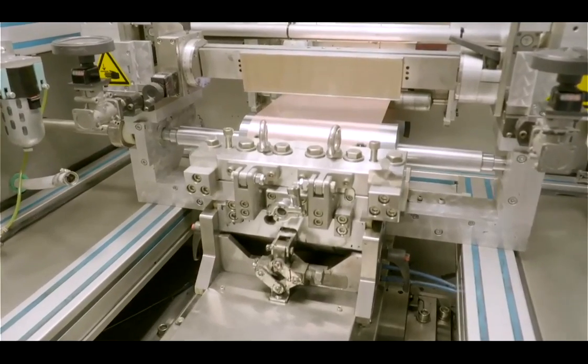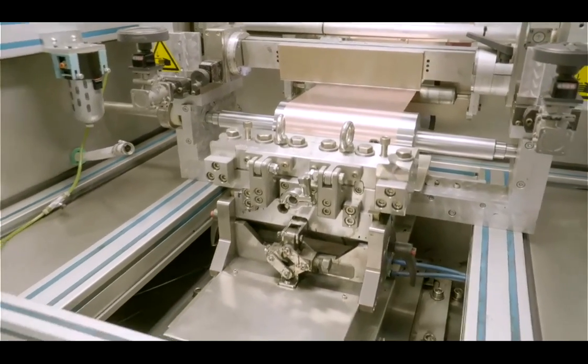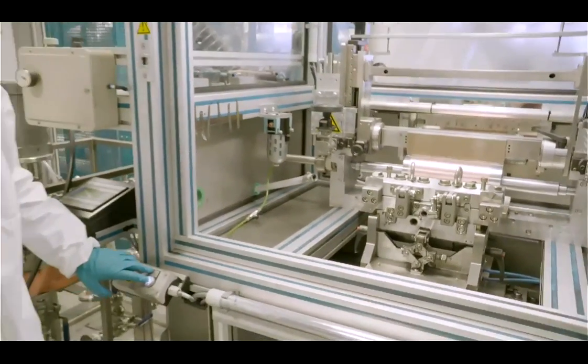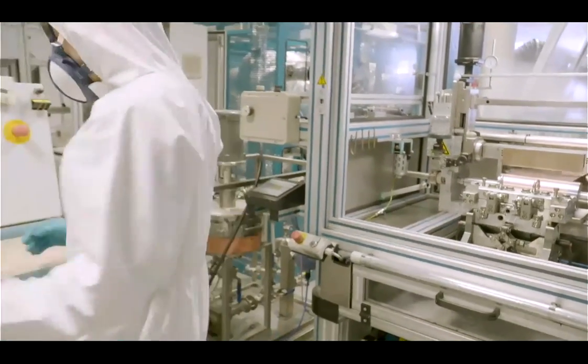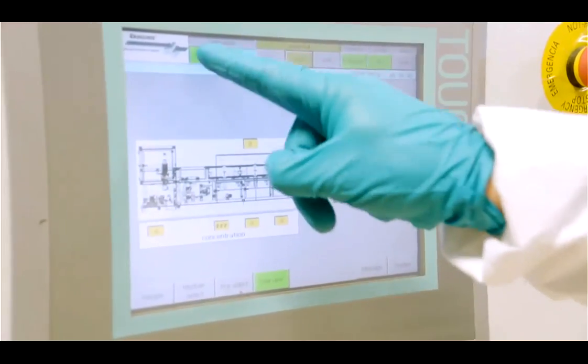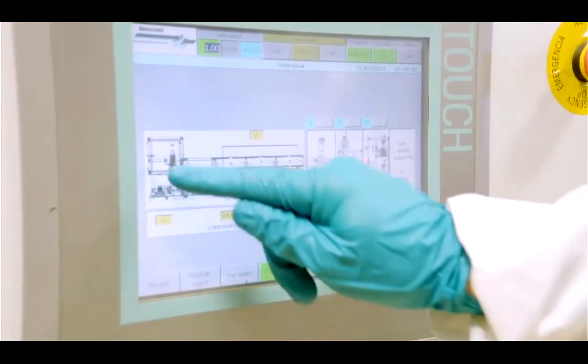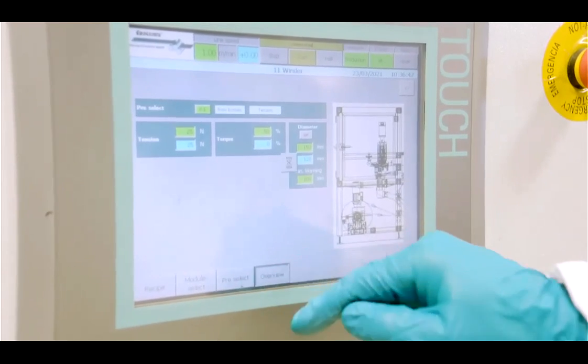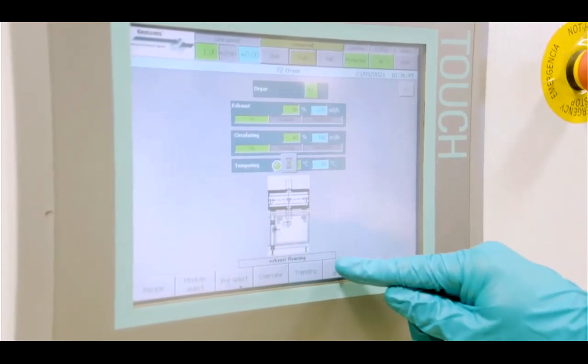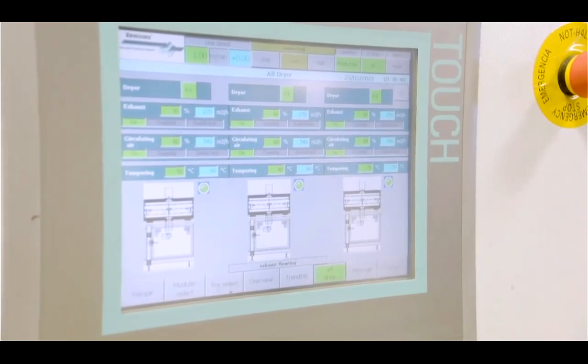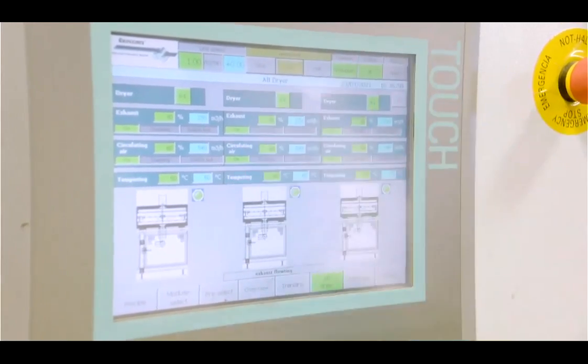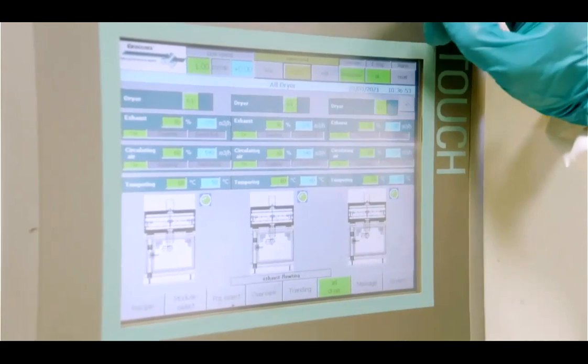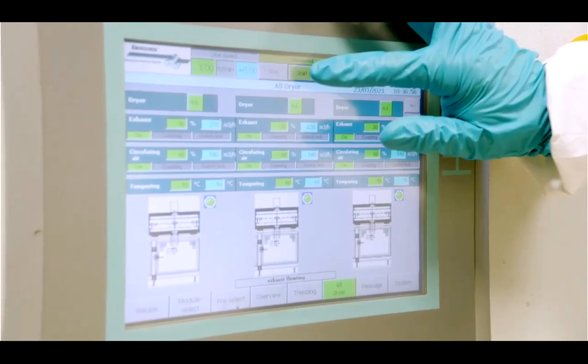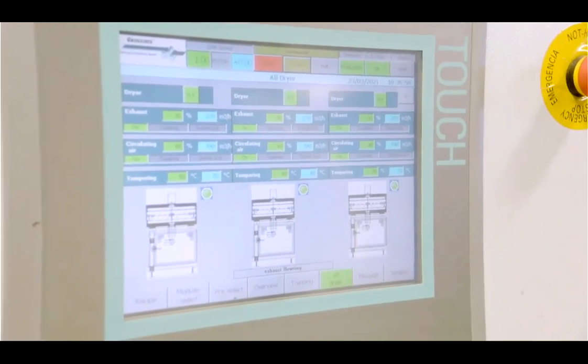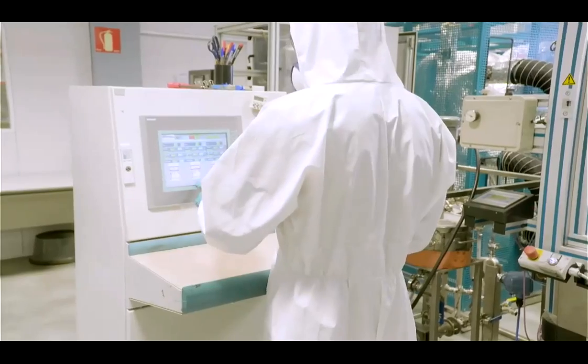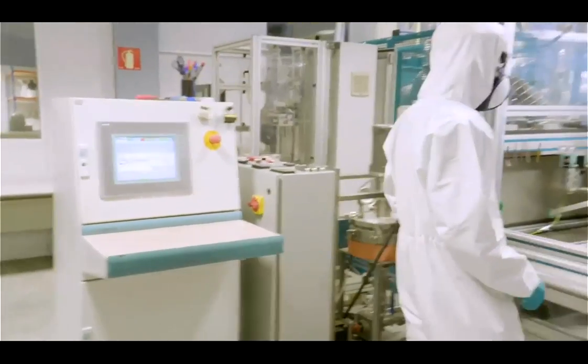Okay, so now let's go to the coating. Once we have prepared the slurries, we have to coat them on copper, or we will coat them on aluminum. The typical thickness of copper we are using is 8 micron, and for the aluminum we are using a 15 or 20 micron substrate. Depending on the type of electrode we want to produce, we will use two different coating heads. We will use the knife system, or we will use the slot die system. Now you will see it in the image.